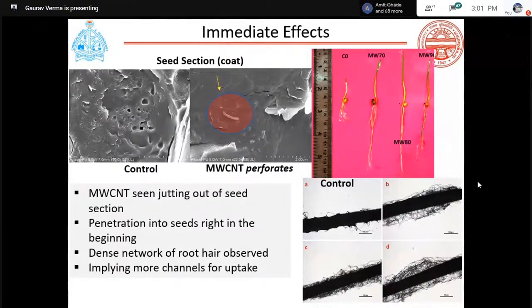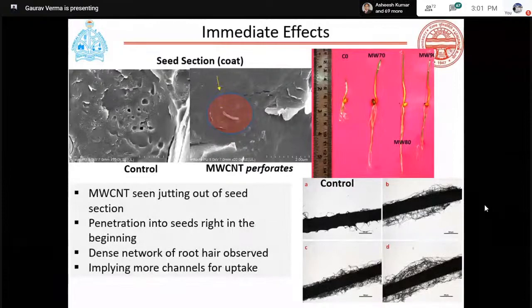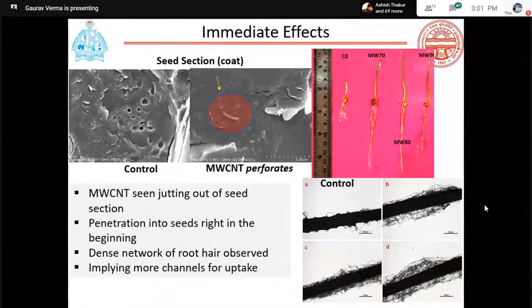But this hypothesis is not understood unless we know what immediately happens to the anatomy of the plant, specifically the roots. So as material scientists or engineers, the first thing which came to our mind as a group was to look into the microscopic root hair which is developing for these primed seedlings. And very interestingly, when you see these images, this dense hair network for an unprimed or a control, you would be surprised at the small micro-sized hair which grew on the primed seedlings, which actually tells you that the plant has not only accepted the carbon nanotube, but positively accepted.